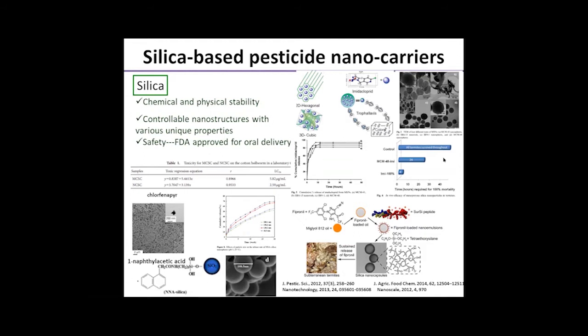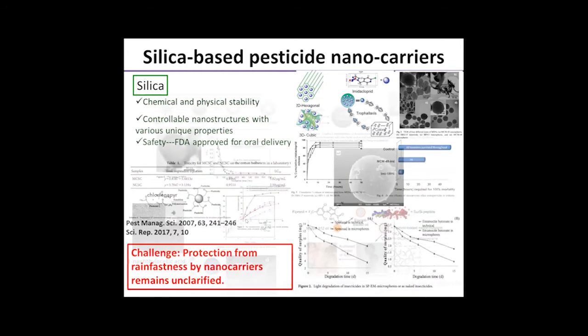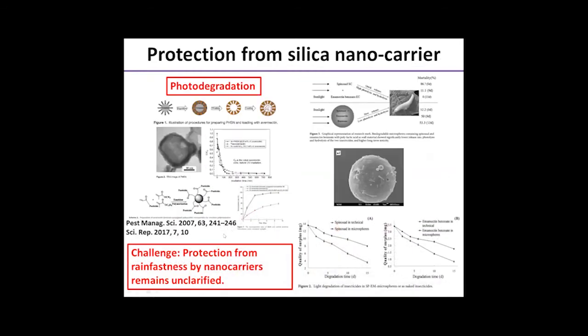These two papers on the right use mesostructured hollow silica and hollow silica nanospheres as carriers of a insecticide, fipronil. The controlled release of the pesticide is the focus of these two works. A recent study using mesoporous hollow spheres to encapsulate the biopesticide ivermectin reveals that the siliceous shells could provide a UV shielding effect and play a useful protection role to address the photo-induced instability issue of photolabile pesticides. Nanocarriers enable photoprotection of pesticides.